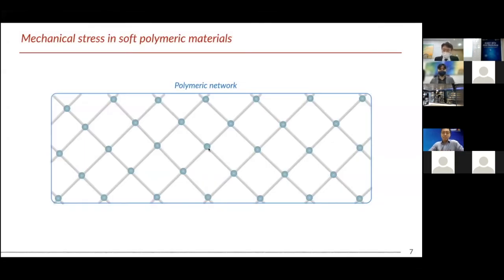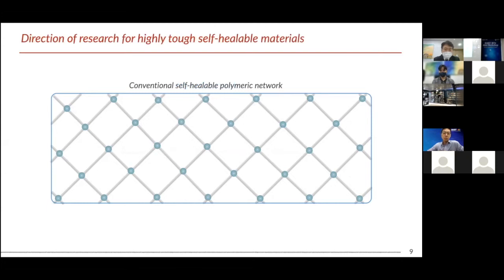Here is the most simplified polymer network for an elastomer. There are flexible polymer chains, cross-linked by chemical bonds or some physical interactions. If we apply mechanical stimuli or extreme stress, some of the bonds will be broken or some physical interactions will be suppressed, and the material will lose its mechanical strength. In contrast, in a self-healing polymer network, even though we apply mechanical stress and some of the bonds are broken like this, they autonomously reform their bonds and can restore their mechanical properties. This is the basic principle of the self-healable polymer network.